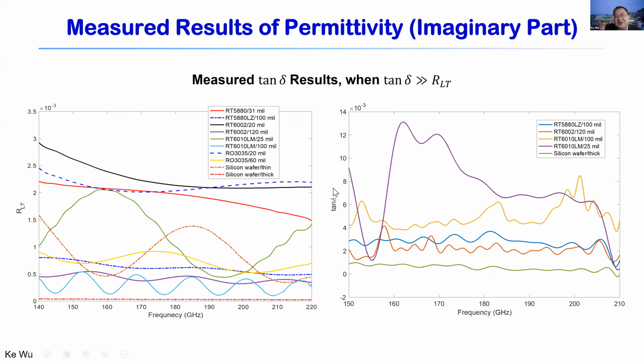At the same time we look at the loss tangent. As I said, the measured loss tangent result should be larger than the loss tangent resolution. So this gives us values right away. For example, the loss tangent value here gives us very good satisfaction, for the thicker silicon wafers. But for the Rogers substrates, the thin substrates, usually the value is not very good. The loss tangent value is not good. To some extent, for thin substrates the loss tangent is difficult to measure, and this is why the loss tangent value here is a little bit frustrating. There is a strong variation over the frequency range of interest.